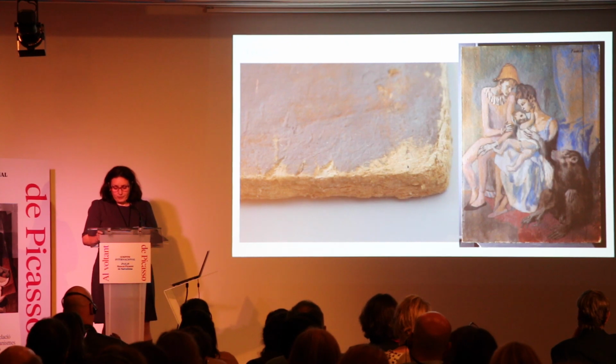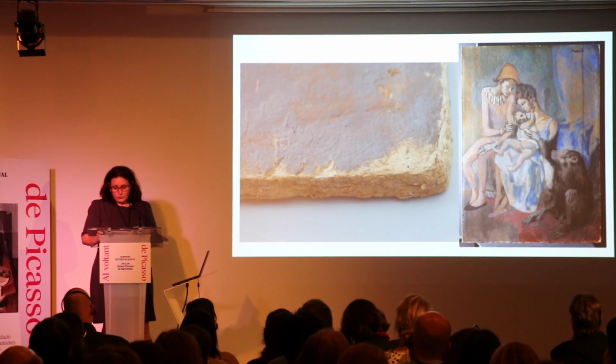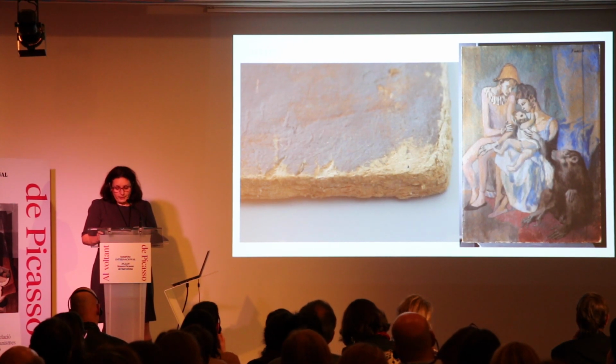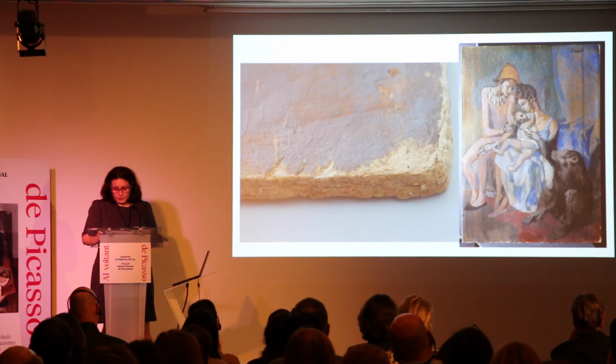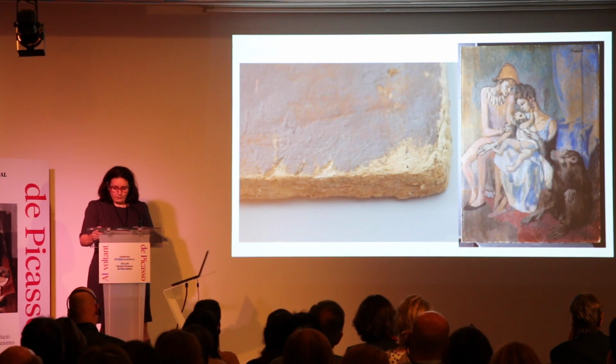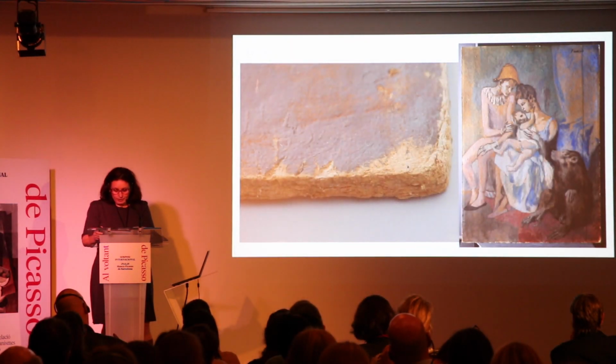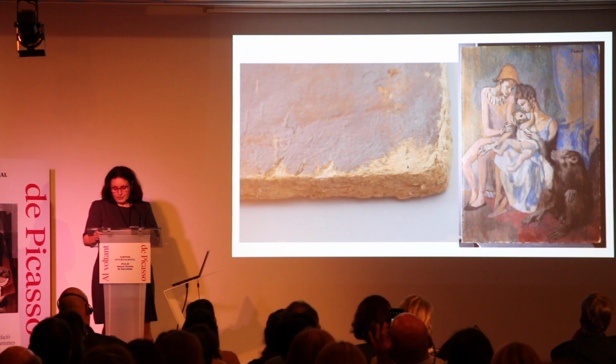The analysis carried out by Eleonora Papa showed that the cardboard is made of highly lignified mechanical wood pulp with some traces of wool and cotton, as was typical of low-quality cardboard. The cardboard is also slightly acidic. The most sensitive and degraded areas are the board's edges and corners, showing a delamination in the layered structure. Under direct light, the support shows no significant planar distortion. With raking light on the right side of the painting, a long crease is clearly visible.